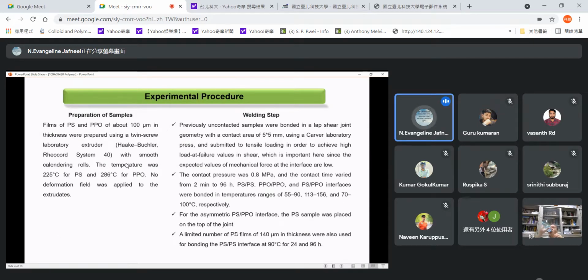The experimental procedure. For the preparation of the samples, films of PS and PPO of about 100 micrometer in thickness were prepared using a twin screw laboratory extruder with smooth calendering rolls. The temperature was 225 degrees Celsius for PS and 286 degrees Celsius for PPO. No deformation field was applied to the extruders.